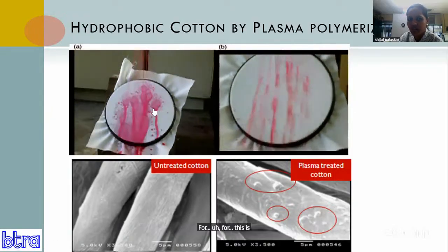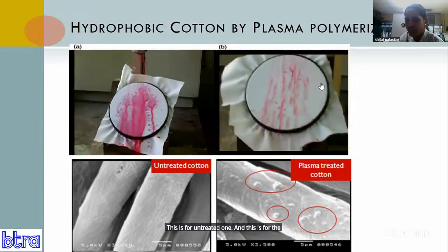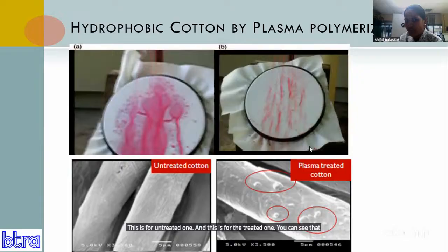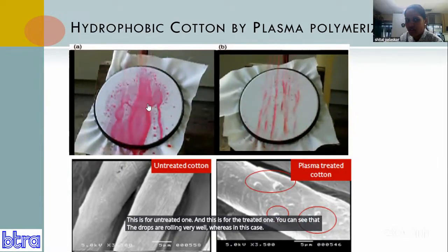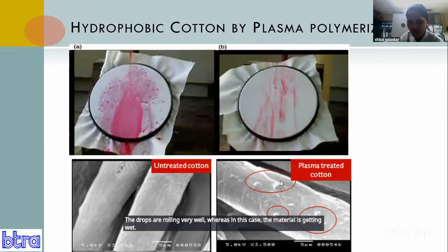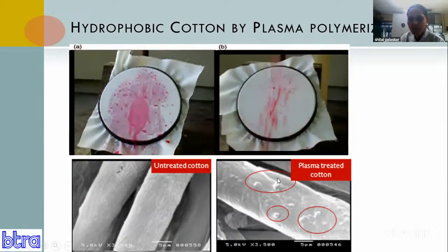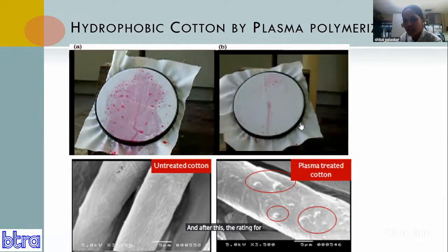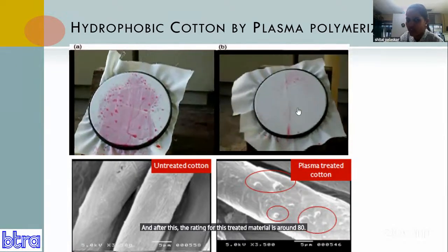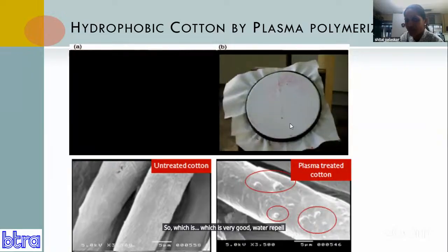This is for the untreated one, and this is for the treated one. You can see that the drops are rolling very well, whereas in this case the material is getting wet. After this, the rating for this treated material is around 80, which is very good water repellent properties. Here we can see that after plasma polymer deposition, a very thin layer of the monomer is deposited, which is mainly responsible for this hydrophobic finishing.